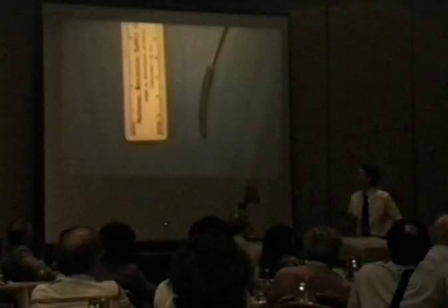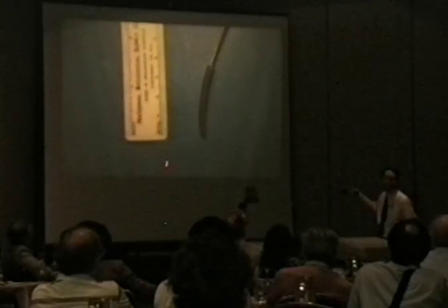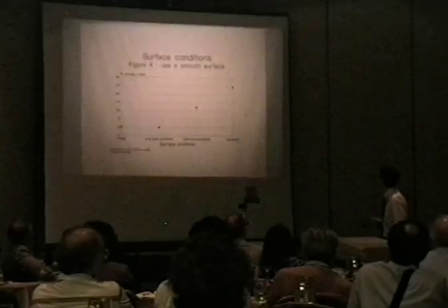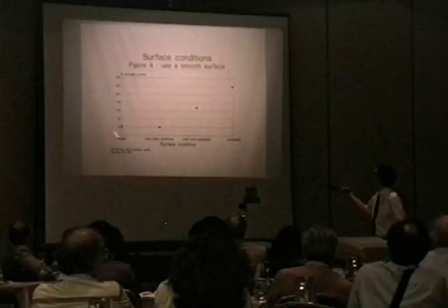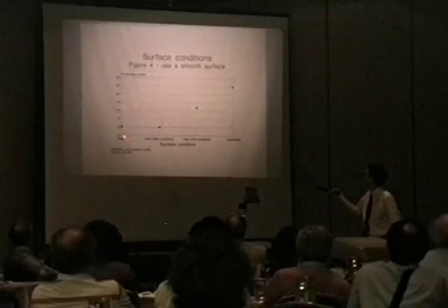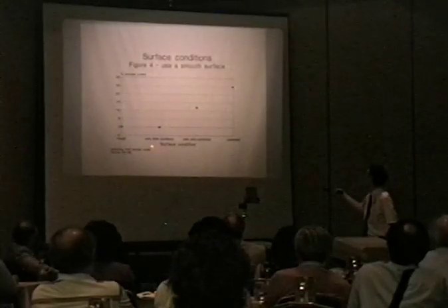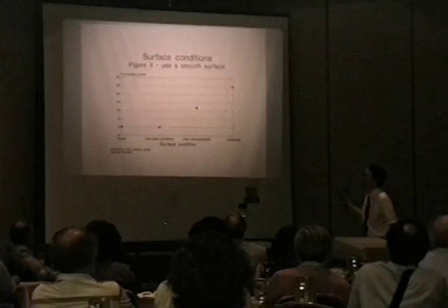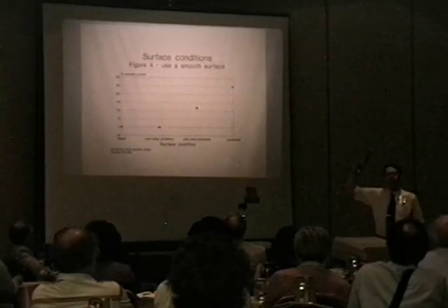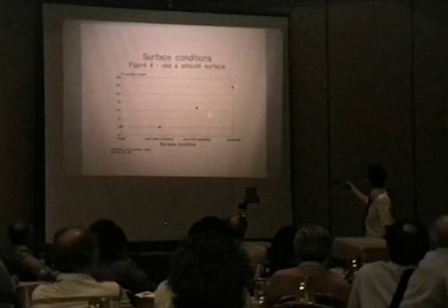And what I believe is happening is that it is causing greater volume expansion, more outgassing, more defects down in the plate. So it seemed to be important to polish these things. I did a series of runs where I had two rough sides. I didn't get any excess heat. I didn't polish one side, didn't see anything. I polished the end and kept the top part rough, and I got something.